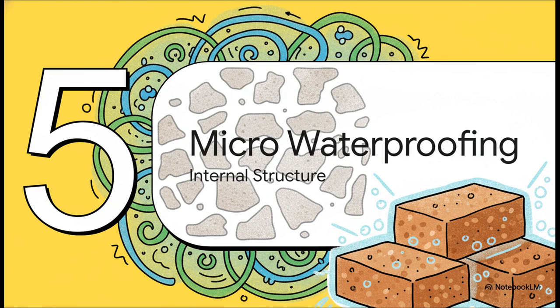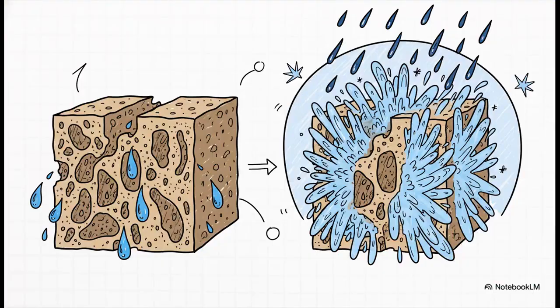Section 5. Micro-level waterproofing. Because this chemical synergy isn't just about raw crushing strength either, it fundamentally changes the internal microstructure of the block itself. Those continuous cementitious reactions we just talked about, the long-term calcium aluminosilicates forming, they actively filled in the interconnected microscopic voids inside the block over the course of those 5 years. And because those tiny pathways were blocked by the new chemical gels, the S3 block's water absorption plunged all the way down to a highly durable 7%. In the real world, that means way better resistance to rain, far less internal erosion, and a drastically longer lifespan for the building.